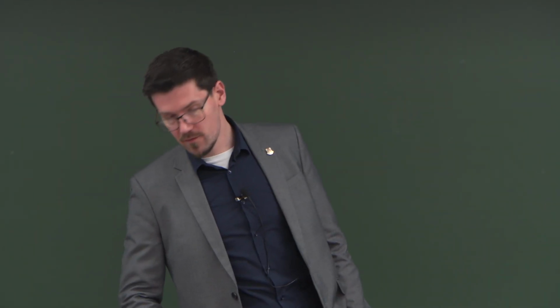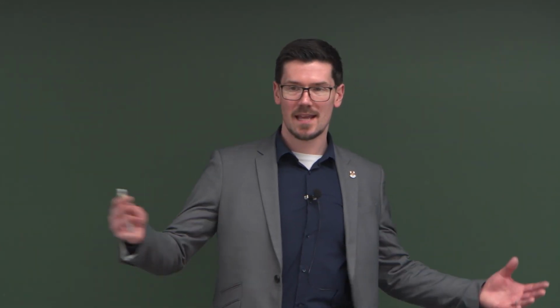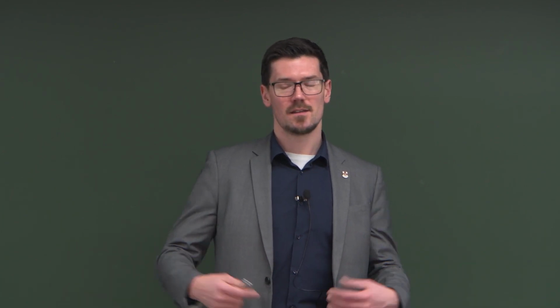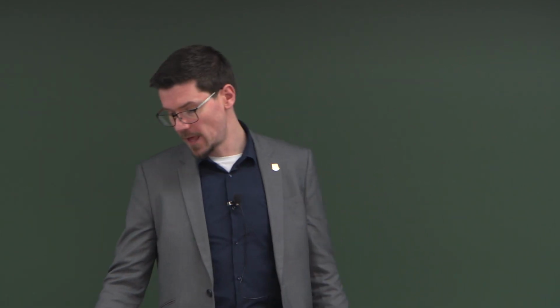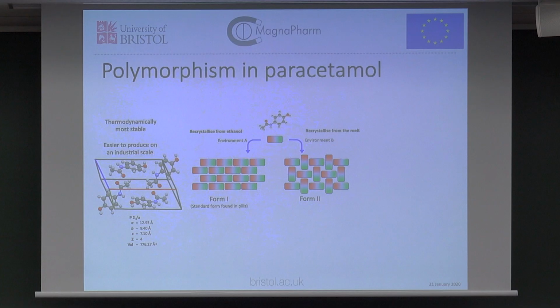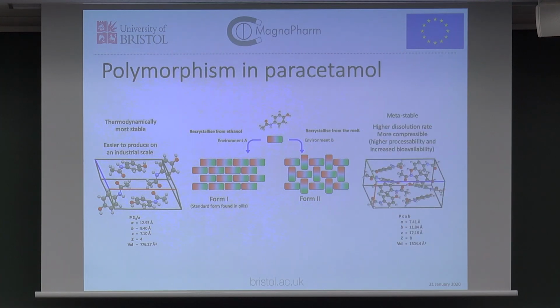However, if you crystallize it from the melt, that is, you just take the molecules as a solid, you melt them and you slowly cool it, you get form 2. Now, the interesting thing about Form 2 is it's metastable, which means at the temperature in which you're measuring, it's not the thermodynamically most stable. Given the chance, given an activation energy barrier, it will transform to the thermodynamically most stable form.